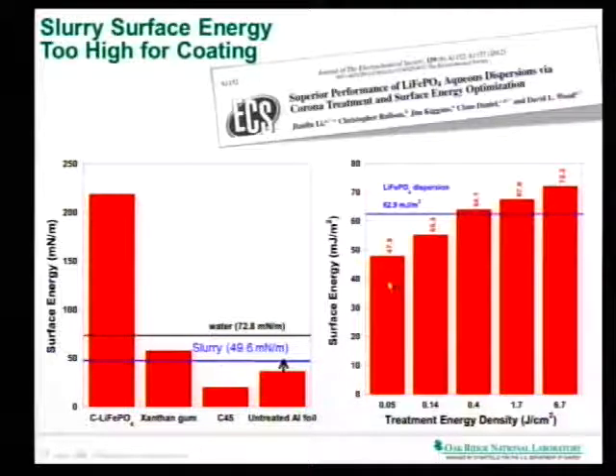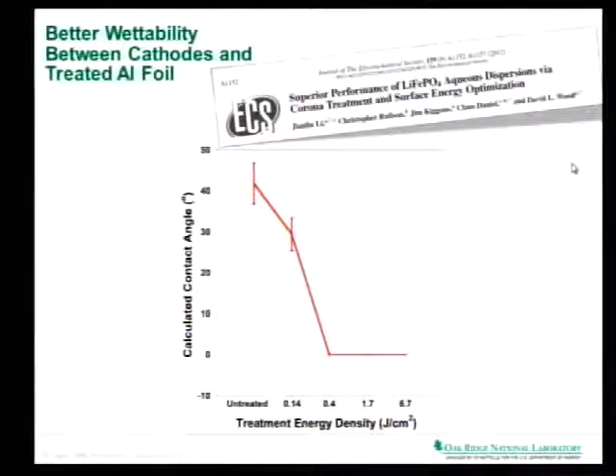And as you look here, as we change the energy of the plasma we are running over our surface, we're able to go anywhere from well below where we had been before to well above the surface tension of our slurry. That now allows you to completely engineer the system very well. You keep your particles afloat in the dispersion, and you are then able to deposit them very well onto your current collector. And voila, when you do that, you essentially drop down to a contact angle of 0. A contact angle of 0 means you have perfect wetting. You put a droplet on your surface, and it spreads out. Exactly the opposite of what we're trying to accomplish with our superhydrophobic stuff, right?